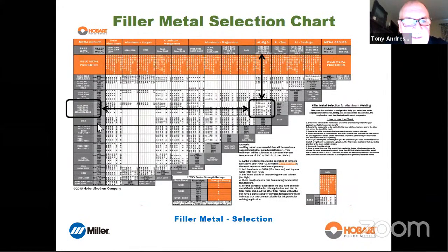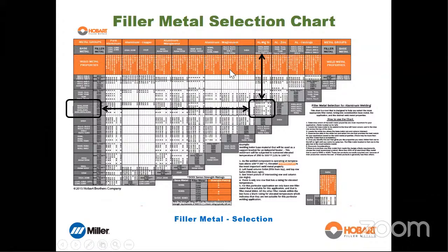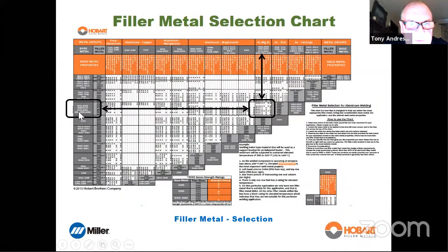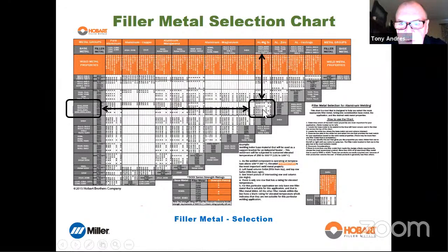All right, so what we've got here is just showing you how you use the chart, essentially. We've got the base alloy, in this case 6061 welded to 6061, and we go to this circle here, and this gives us all the filler alloys that you can use for welding 6061. I believe there's 7 of them or 8 of them. 1, 2, 3, 4, 5, 6, 7. There are 7 filler alloys listed, and you can choose any of them to weld 6061. However, depending on your application, you may choose one of these over the other, most definitely. For instance, if you're going to anodize, you would not choose 4043 because the weld would go black. You would use 5356.